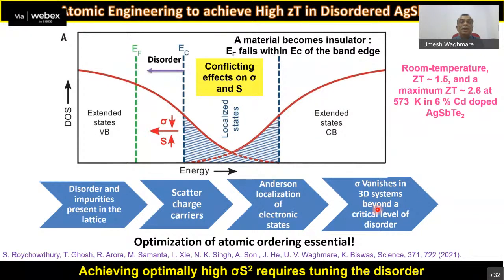in 3D. And once you have disorder, and if your Fermi energy of a material is here, you have an insulator, no high conductivity. But if you dope it, you can move the Fermi energy down. This is called the mobility edge. Once you cross the mobility edge, you can have a conducting semiconducting material, and vice versa, n-type and p-type.